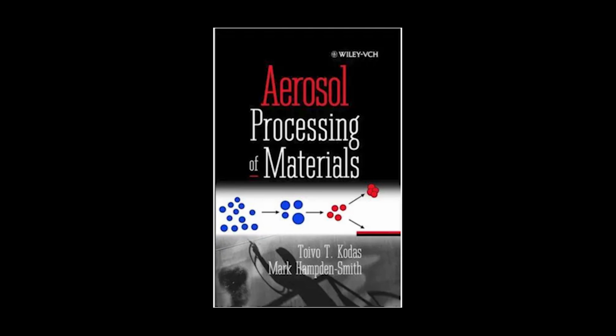The book gives a great example. Sintering 10 nanometer TiO2 particles takes about 1,000 seconds, around 16 minutes at 800 Kelvin. If you raise that temperature by a few hundred degrees, that time might collapse to seconds. This reveals the razor's edge an engineer has to walk. You need high temperatures to drive the chemical reaction, but if the temperature or the residence time is too high, the particles fully sinter and you lose the desirable nanophase characteristics. You are constantly managing the race between reaction time, collision time, and sintering time. You have to design the reactor to do the chemistry, then rapidly quench the process to prevent unwanted coagulation and oversintering.